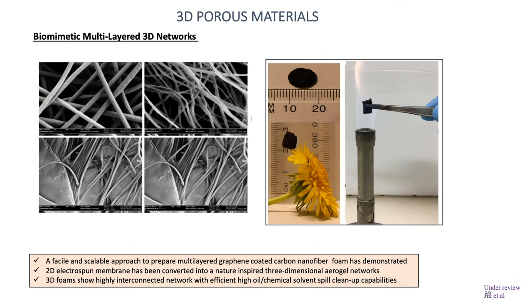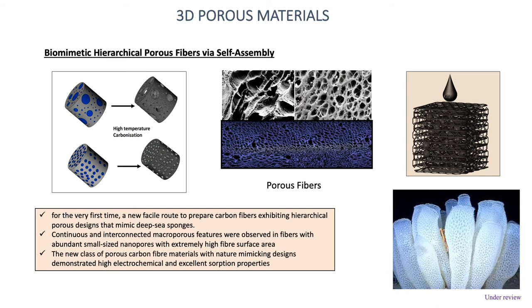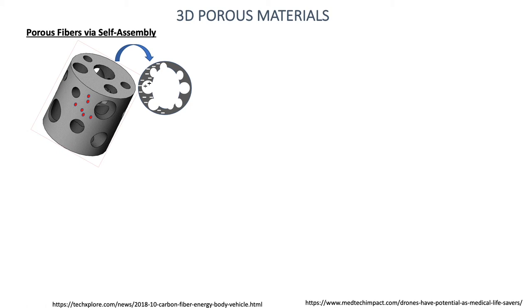In our current research, we combine the self-assembly approach with adding functionalities, mainly working on carbon materials and converting 2D materials into 3D materials. In this work, we brought functionalities like high fire resistance, high absorption properties, and energy storage. We also wanted to look at what happens when we scale up self-assembled nanostructures at macroscales. We demonstrated this by making functional fibers — marine sponge-inspired fibers exhibiting meso-, micro-, and macro-sized porous features on both the surface and cross-section. These fibers exhibited high surface area, high oil adsorption property, and energy storage. Using a self-assembly approach, we developed scalable formulations for highly porous carbon fibers with unique interconnected pores.